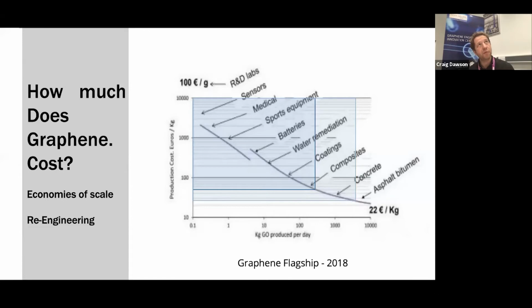And we've seen with one of our current projects, where we were putting graphene within cement and concrete, that the effect graphene's had on the system has meant that they can do extra things. Especially with sustainability in mind, we've cast concrete floor slabs with enough early tensile strength that it's allowed us to take the steel support out of the floor slab. So there's a cost saving from a labour and materials point of view, as well as a sustainability saving, a CO2 saving, because we can remove that steel and we can remove up to a third of the concrete as well. So it's quite a good success story.